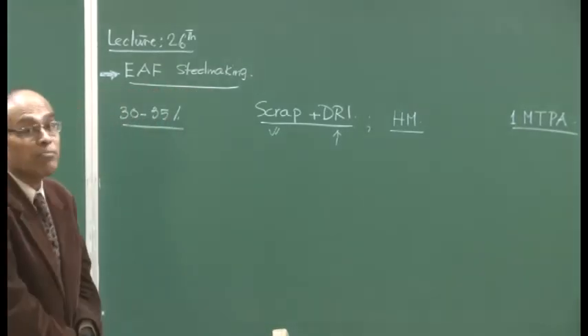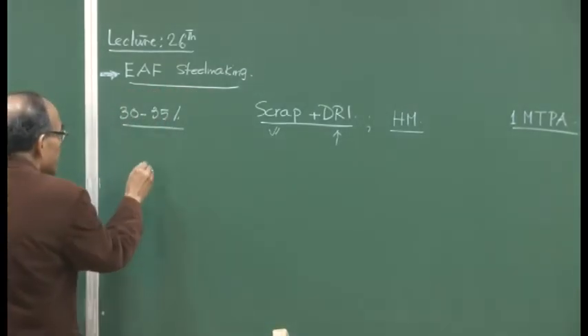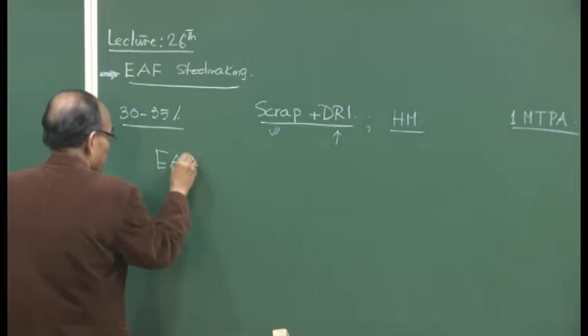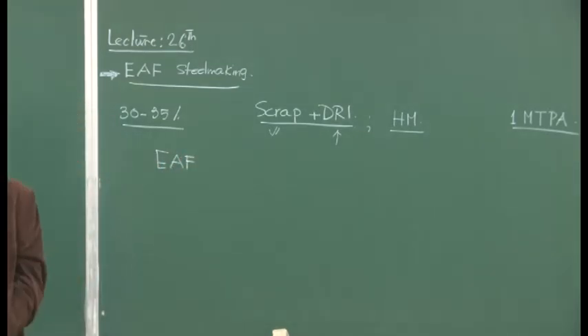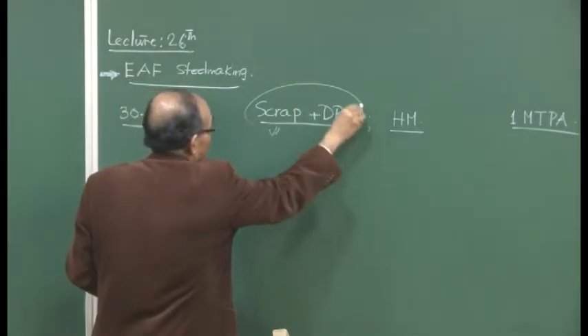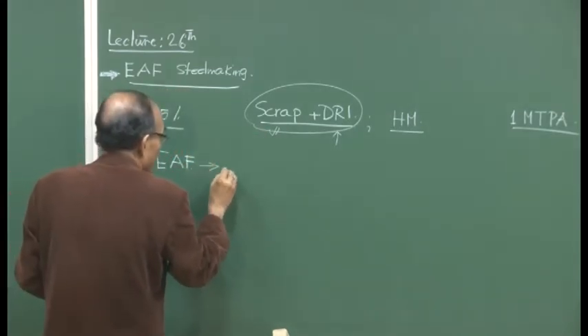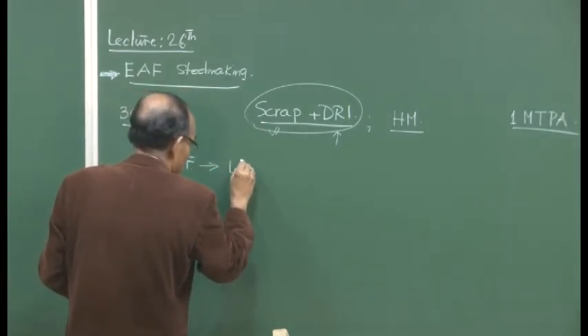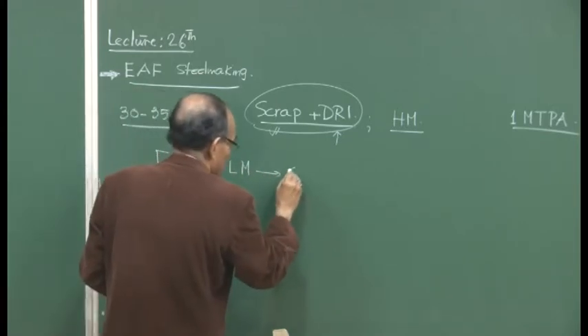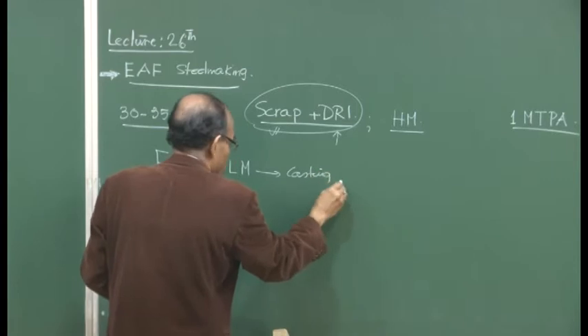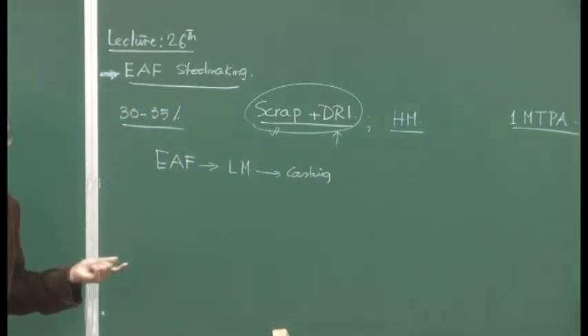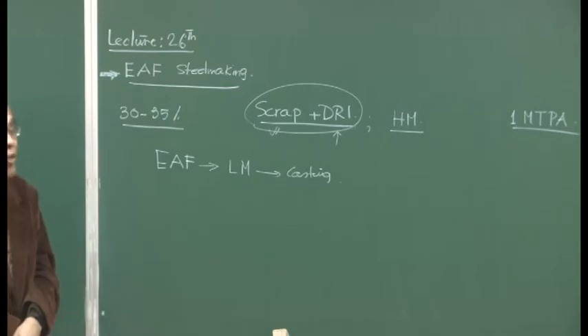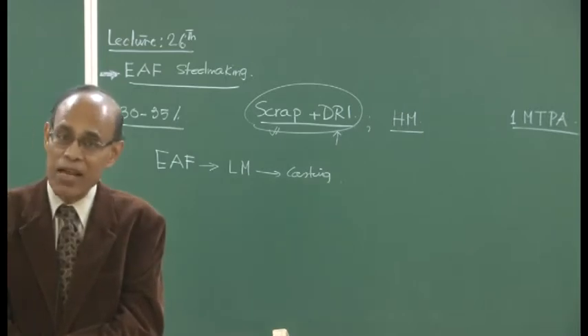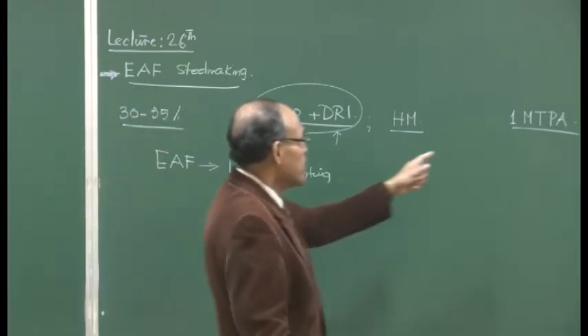These are special steel plants where we have exclusively EAF, and because there is no availability of raw material like hot metal, they are basically scrap and DRI based plants. Then you have EAF, then you have ladle metallurgy or secondary steel making, and then you have casting. Very simple plant, no blast furnace, no hot metal, and these are small plants not producing the carbon grade of steel. Okay? Carbon steel, for example; they are producing specialized products because their productivity is much smaller.